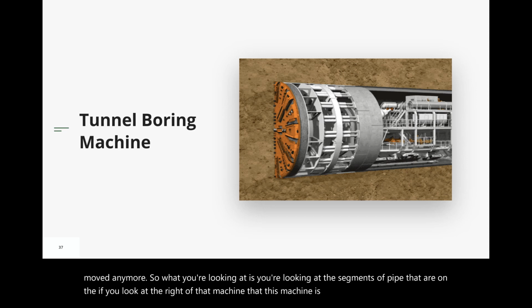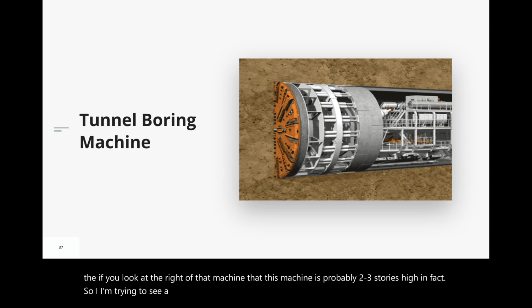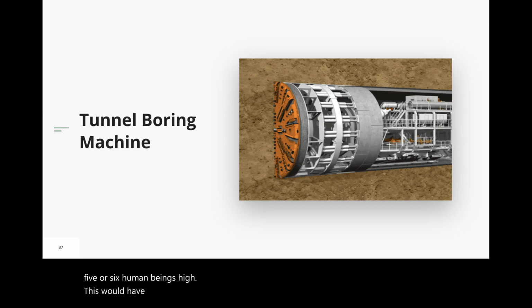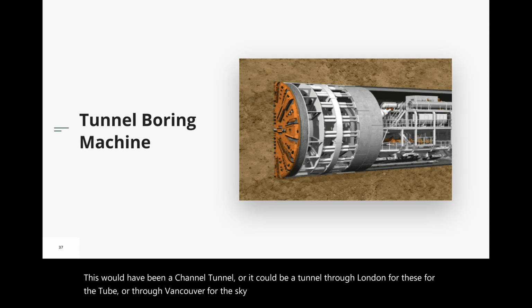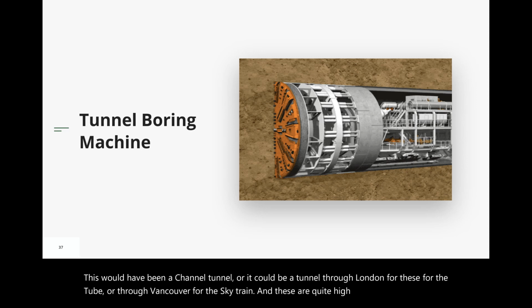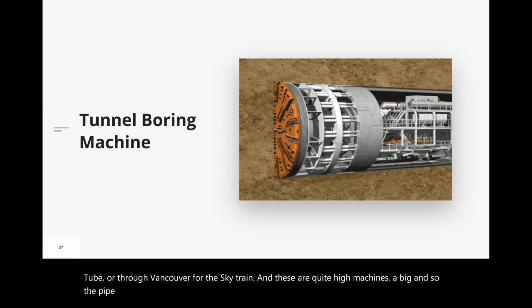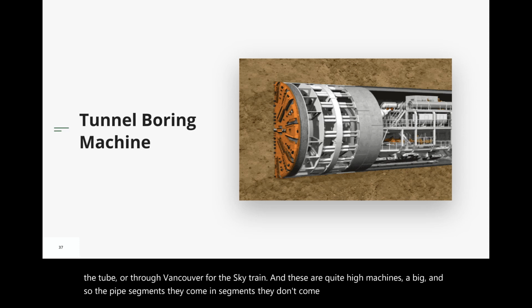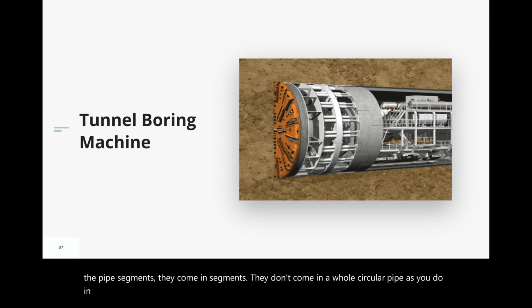They don't come in a whole circular pipe as you do in microtunneling. It comes in segments. The segments are on the top, and you can see the segments on the side there as they're put together. And so the segments are put in place, and then the machine actually pushes off those segments to go again. And it keeps on going that way. So the segments, once they're put in place, they don't move anymore. So therefore, the only friction in this is the friction between those segments and the front end of the cutting machine. That's the only friction, which means the friction is very, very low, which means you can go, there is really no limit as to the distance you're going.